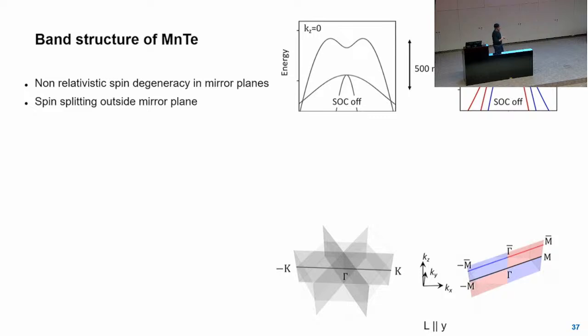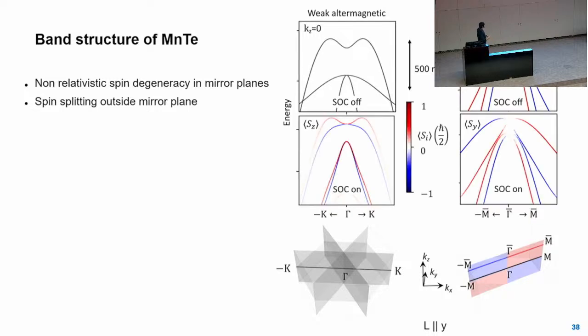And then of course in real life we cannot turn off this interaction of the spin and its environment, so we have to do these calculations with this effect considered. And when we do that, it's getting a bit more complicated, but in the end, in this picture, the main picture stays the same. It's a small correction. Here in the case where there was nothing before, it turns out that there is also some finite effect coming, so it's even getting, let's say, more interesting.